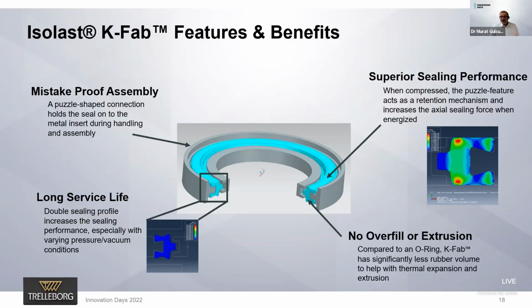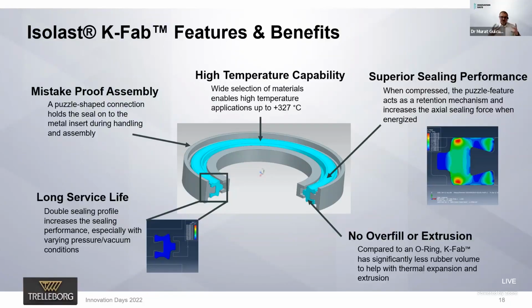And of course, we replace some of the mass of this seal with metal. You can see it on the outer ring. That also helps with the expansion of the seals, especially at higher temperatures. So KFab seals don't really overfill, or extrude at high temperatures because of the expansion. And finally, high temperature capability. Because this is a product we can make in any material that we have in our portfolio, we can make it in ultra high purity materials where high purity is needed, or other standard materials. We can make it in ultra high temperature materials, so we can go up to 327 degrees, for example, especially in the exhaust line. Sometimes temperatures can go above 300 degrees, so that is quite critical. So this summarizes everything about KFab seal.